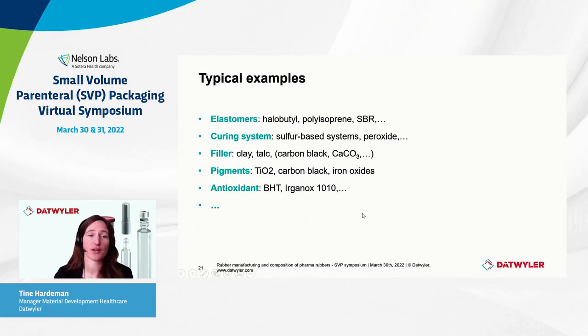Okay, quickly having a look at the other ingredients. So for cure system, of course, this depends on the type of cure system that you're using. Sulfur-based cure systems are the classic typical ones. This can either be with sulfur itself or sulfur donor systems, but there are also other options such as peroxides, resins, and some other novel cure systems. Then for the filler, as I mentioned already, clay and talc are very popular for healthcare. For other industries, such as, for example, for tires, carbon black is a popular filler material, but this is really avoided in the healthcare segment. And you, for example, also have some calcium carbonate in older grades, but also in modern formulations, you will not find it that much anymore.